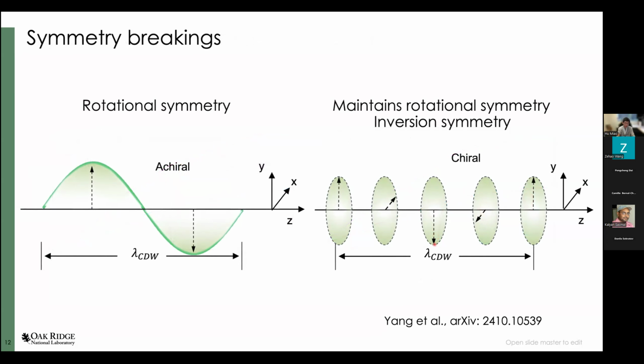Once you can experimentally establish a transverse Peierls transition, that opens up a lot of new possibilities. For example, if you imagine a transverse lattice displacement as shown here, and you look along the z-axis, you would expect the rotational symmetry of your material to be broken by the transverse CDW. That will end up as a C2 charge density wave, or C2 transverse Peierls transition. On the other hand, you can also have a lattice distortion that is chiral. In this case, you can preserve the rotational symmetry, but you break inversion symmetry, and you will realize the chiral CDW. So the key point is you first need to realize the transverse Peierls transition, then you have all kinds of different charge density wave patterns.